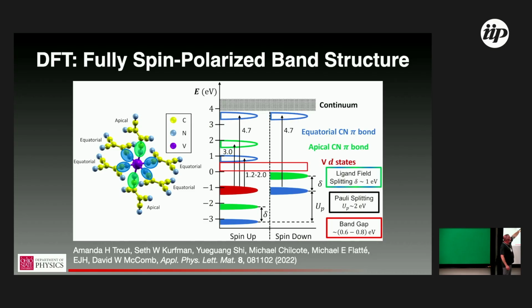And so the equatorial TCNE all talk to another vanadium. So you form sort of a sheet of vanadium and TCNE, but then the bridging between those sheets, we have these apical TCNE, which only have 2 of their cyano groups coordinated. So these diagonal cyano groups, on average, if we were to form a perfect crystal, don't have any coordination here. And that does a lot of interesting things, which I'm sort of diagramming on the right here.